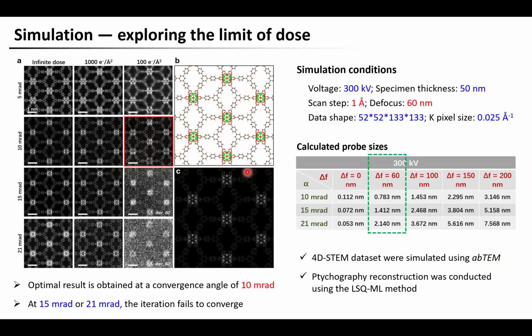In the TEM community, many groups have made significant efforts to push the resolution limit of ptychography. Resolution better than 20 picometers has been achieved by different groups, which is indeed very impressive. Our focus is a little bit different. We are trying to push the limits on electron dose. So we were wondering whether ptychography can be performed at a dose level as low as, let's say, 100 electrons per square angstrom, to make it useful for highly beam-sensitive materials. We first used simulated 4D-STEM data, and we found that at such a low dose condition, even with the simulated data, the reconstruction is very challenging.